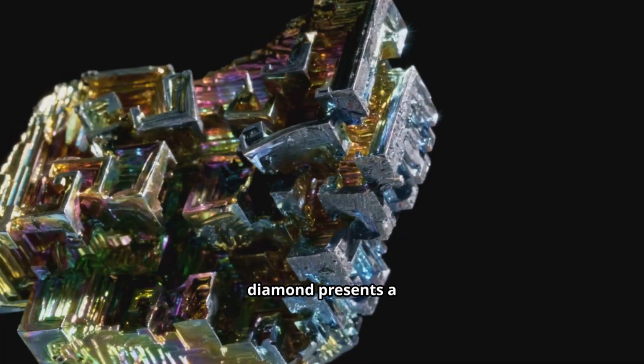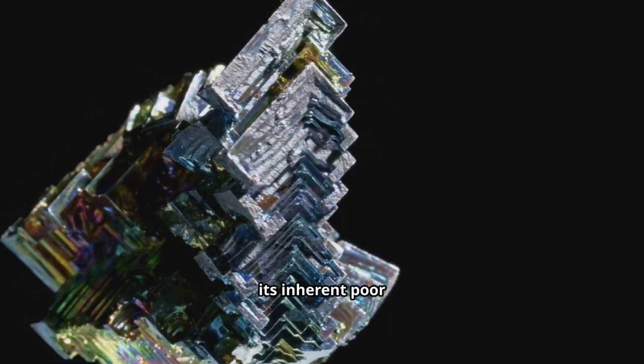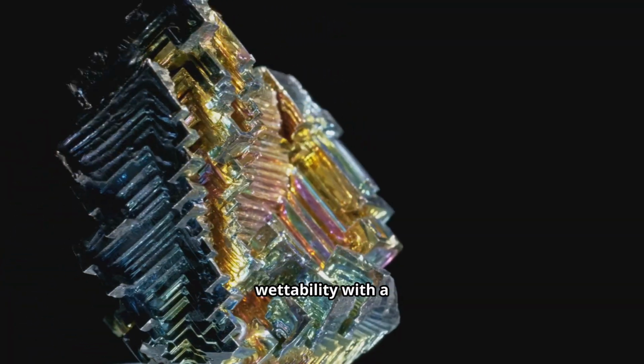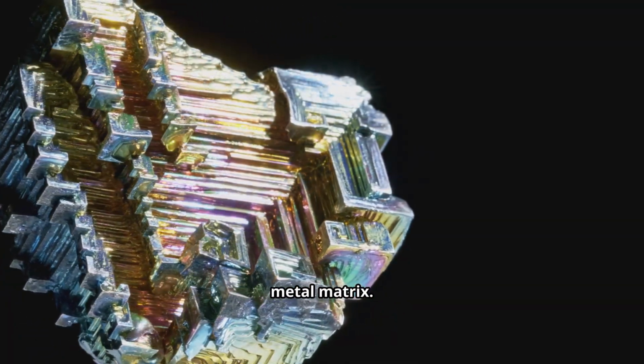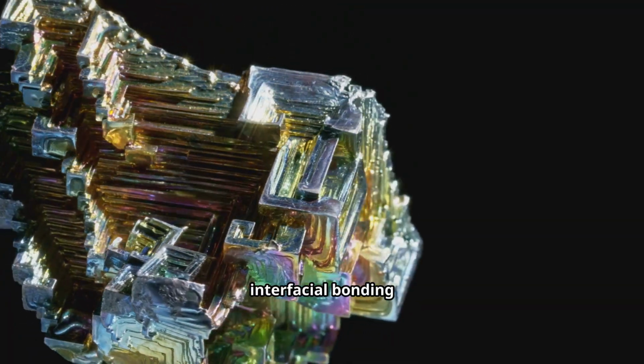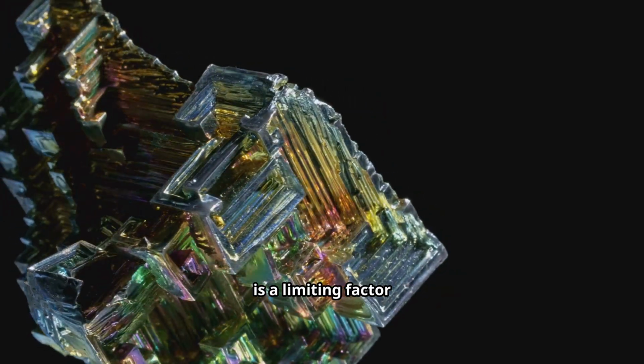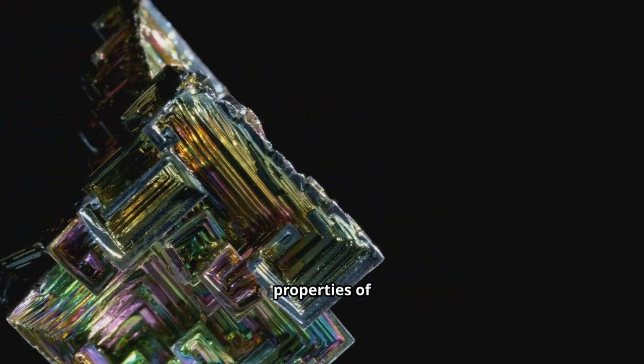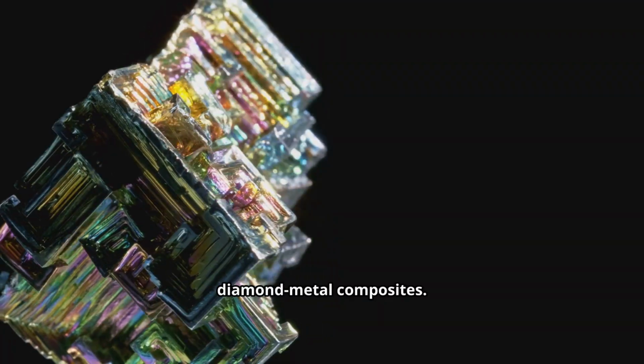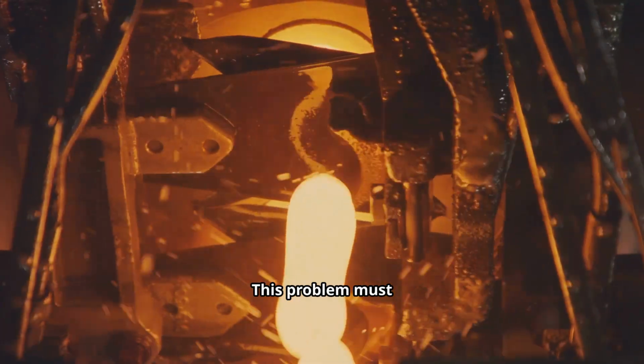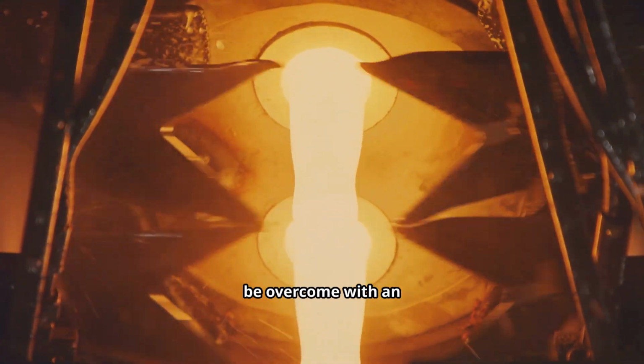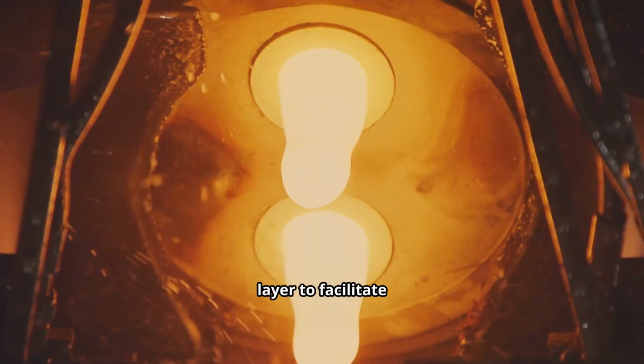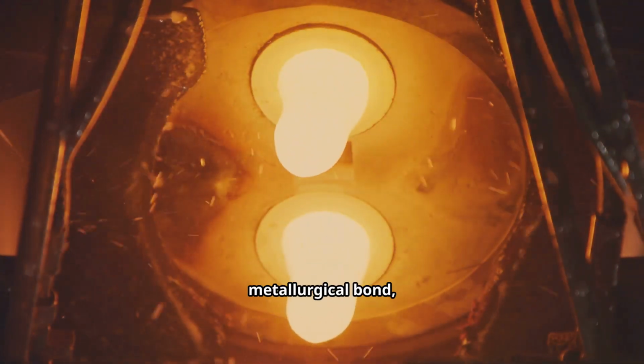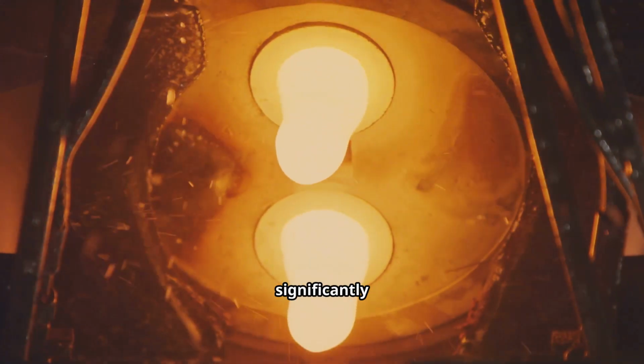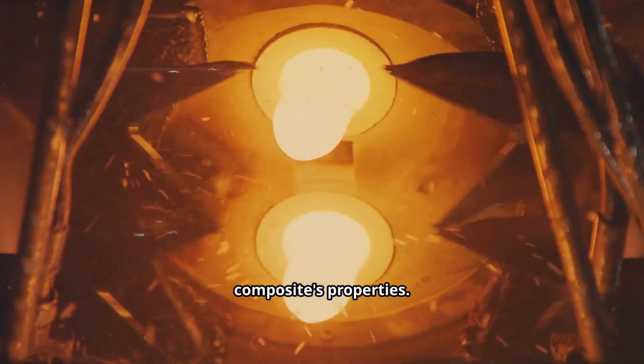However, diamond presents a major challenge: its inherent poor wettability with a metal matrix. This poor interfacial bonding is a limiting factor for the thermal and mechanical properties of diamond metal composites. This problem must be overcome with an intermediate carbide layer to facilitate a strong metallurgical bond, which can significantly enhance the composite's properties.